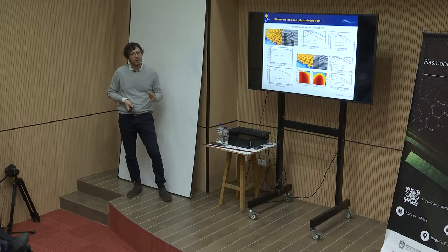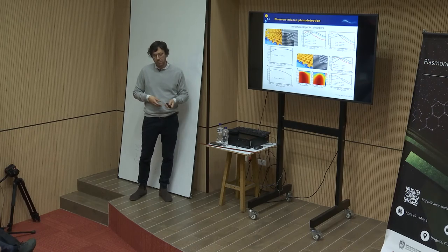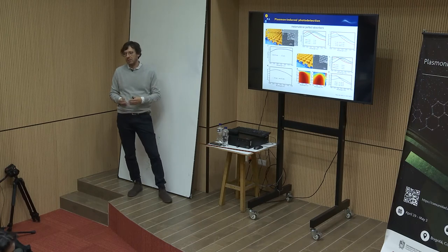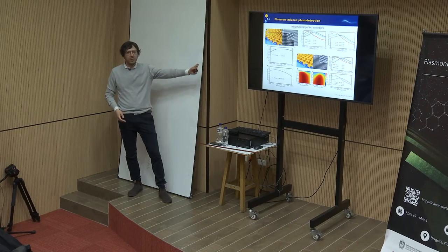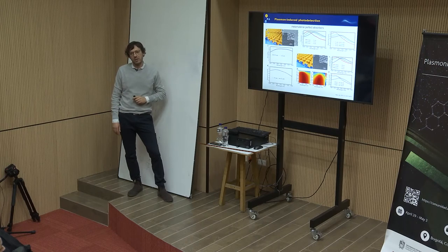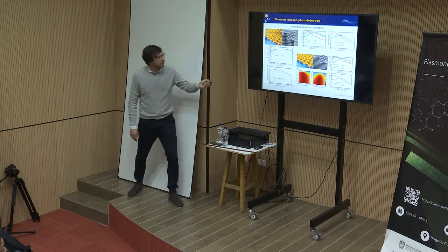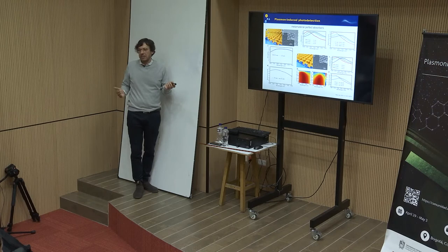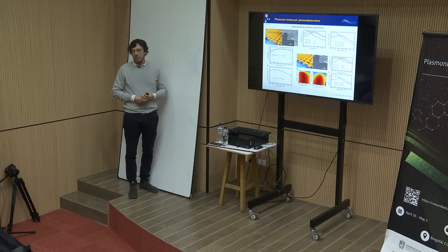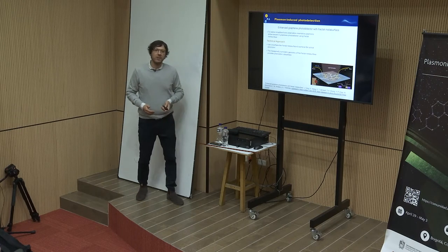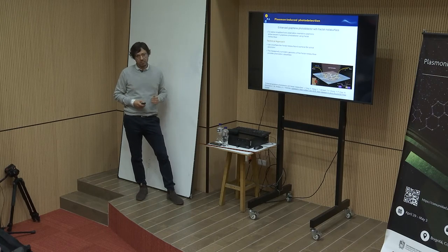Exactly, and so following this, I think it is more promising for catalysis, for example, where we have small nanostructures and this momentum constraint is somehow released. But in this case, we are always talking about hundreds of nanometers nanostructures, where this restriction of physics is really strong. And indeed, here the photoresponsivity is very small. So maybe with different materials coupling, with different nonlinear effects, we can enhance this photodetection or injection. But so far, it's just a fundamental way how we can use the photoelectrons injected from the surface plasmon.